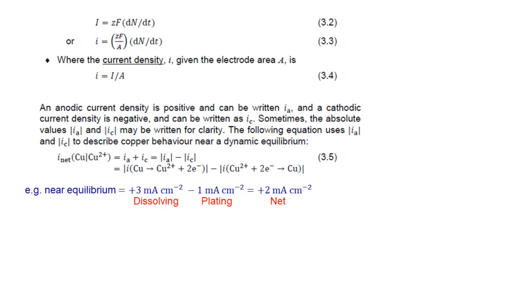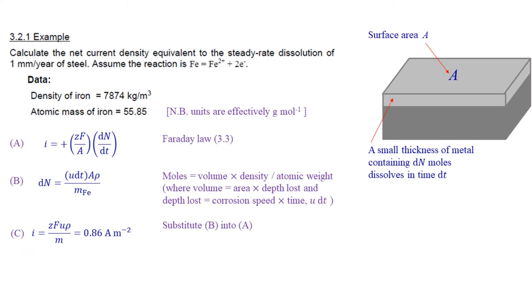So we'll need this idea of dynamic equilibrium in section 3.5 when we invent an algebraic model for electrochemical kinetics. For now, let's go back to thinking about net corrosion current density. In this example, 3.2.1, Faraday's law of equation 3.3 is used to relate the net corrosion current density and the corrosion speed of the metal in millimeters per year. Okay. The example is this. Calculate the net current density equivalent to the steady rate dissolution of 1 millimeter per year of steel. Assume the reaction is iron, Fe, metal, goes to Fe2 plus dissolved ions, releasing two electrons. We have some data, the density of metallic iron and the atomic weight of iron.